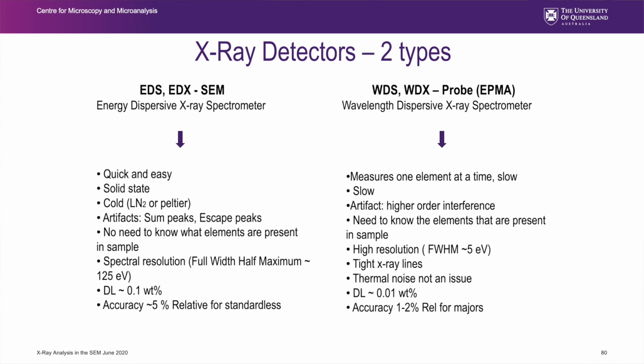However, the WDS detectors are slow, they only measure one element at a time. Because you only measure one element at a time, you need to know what you're looking for, otherwise it takes too long. There's very little spectral artifact, but you can get higher order diffraction peaks. I'll talk about that later.